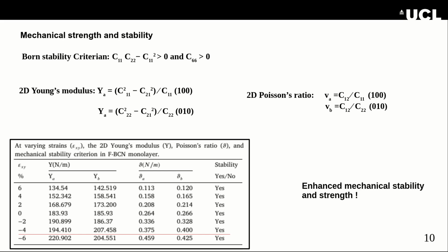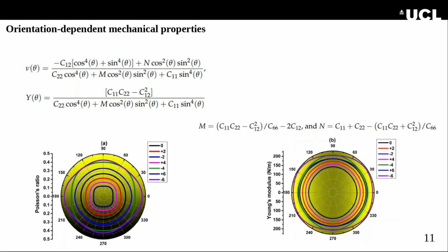The compound boron carbon nitride in fluorinated form shows mechanical strength up to 220 Newton per meter when it is compressed by 6%. Further, we checked the orientation dependent mechanical properties, and we found that the material exhibits isotropic mechanical response. We implemented these relations to compute this polar plot, and it clearly demonstrates the isotropic mechanical behavior, which was lacking in the pristine form.